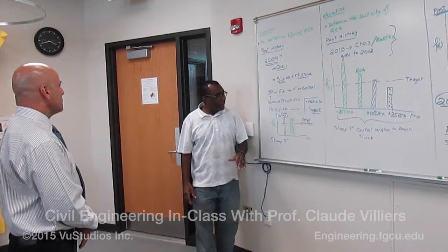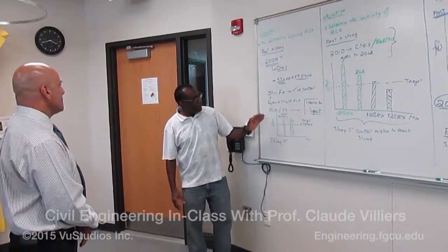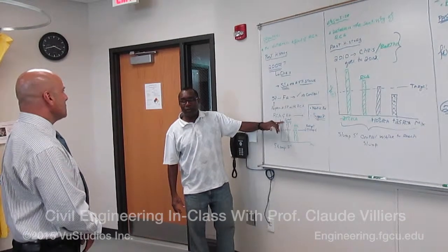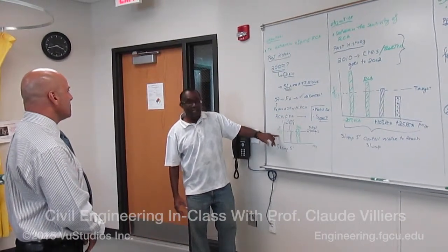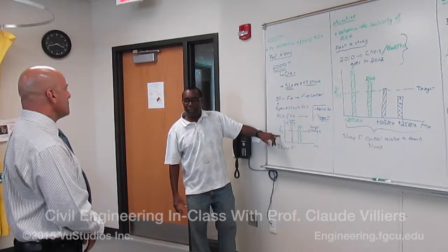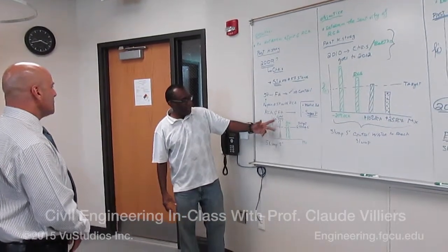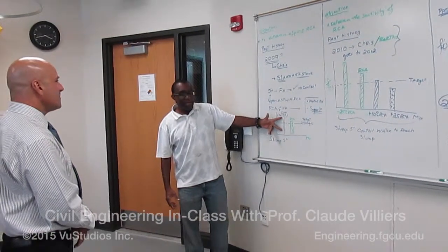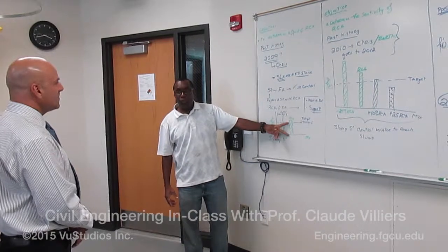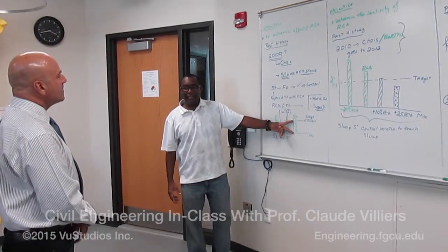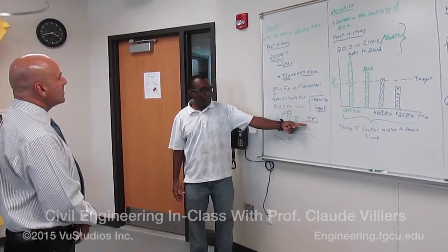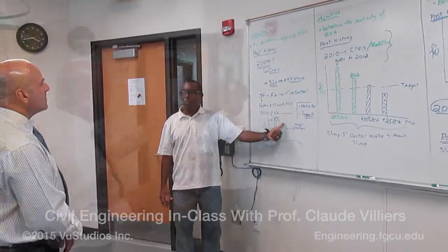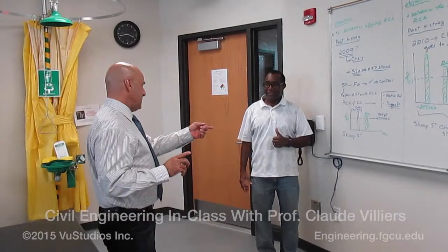That's why I implemented in my course where I had the students design a mix with no recycled coarse concrete and we test it. F'c is the quality of the mix that we see at 28 days. What we have seen in the past, the mix with no recycled coarse concrete gives you better strength than the one with recycled coarse concrete. Now that sounds bad. But remember, my target was to be 2,500 PSI. The recycled coarse concrete met the target and above.